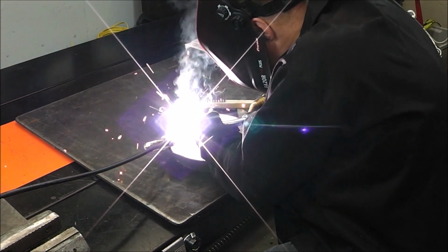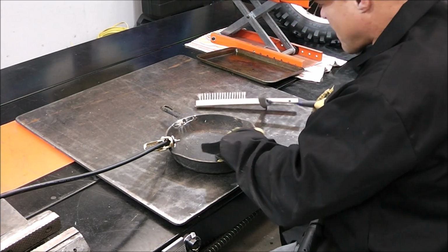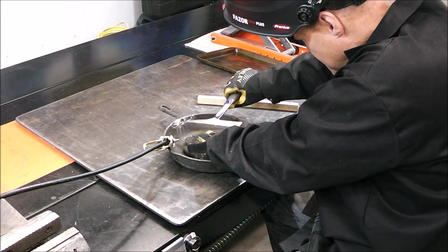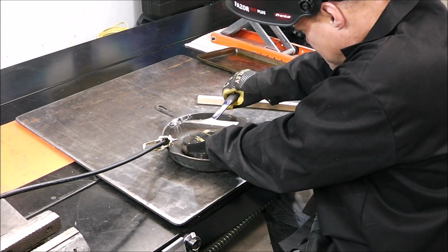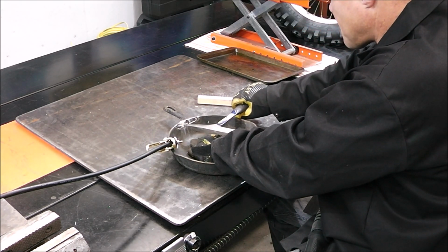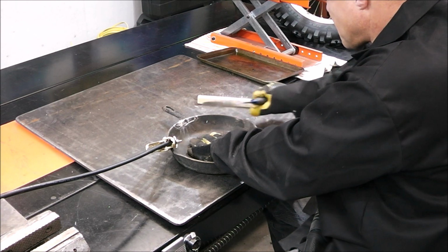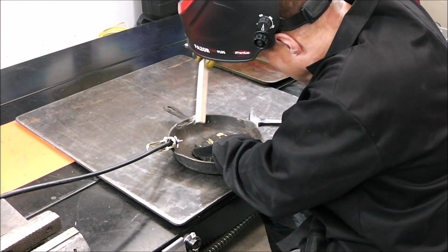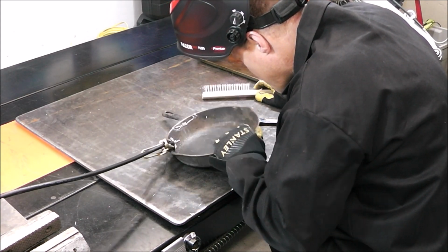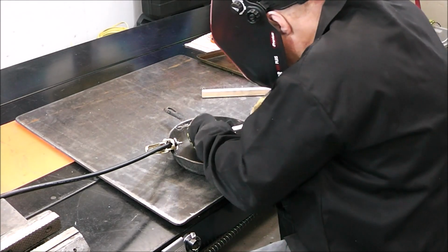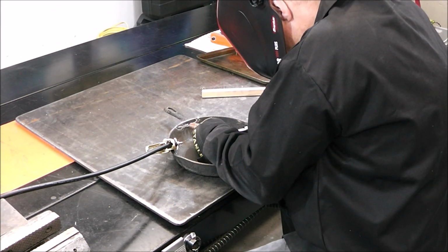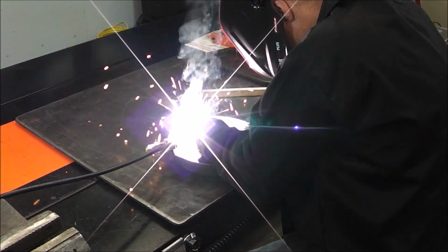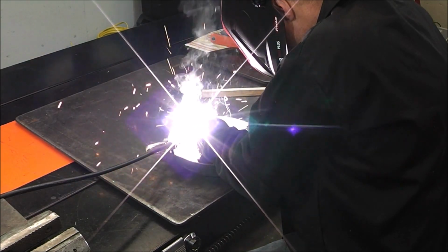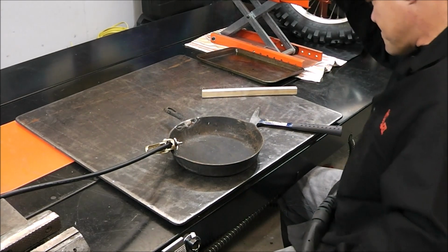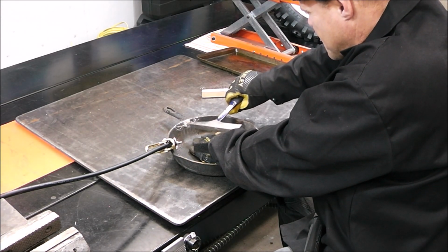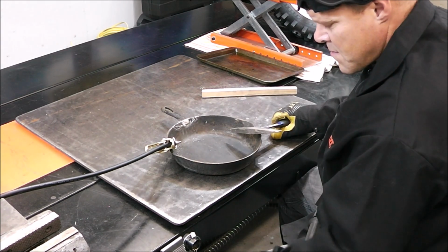Now, whenever cast iron is subject to heat and cold cycles, like let's say an exhaust manifold, it will be more subject to cracking. The reason for that is because it's going through constant temperature differentials, hot and cold, and as we've already spoken about, cast iron has a tendency to harden after you weld it. It becomes brittle. That's why it will always break at the toe of the weld, because that's within the heat affected zone of the weld. So when selecting a filler metal, generally you're trying to find a filler metal that has some elasticity to it, in other words, something that has the ability to stretch or elongate with that expansion and contraction of the cast iron. So if you're welding something that is constantly going through heat cycles, it will have a tendency down the road to potentially crack again because it's going through those swings.